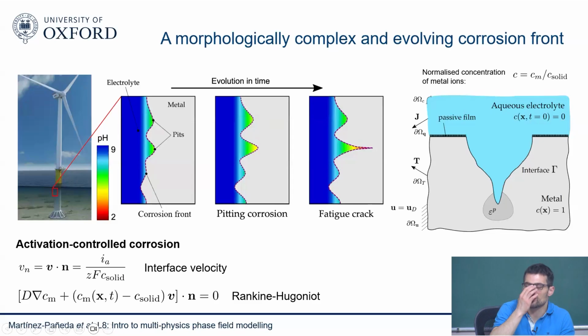And then, what happens in corrosion is that we have two scenarios. One is called activation control corrosion. The other one is called diffusion control corrosion. In activation control corrosion, we do know that the velocity of the pit, this is what you're seeing here, is governed by Faraday's second law. So you have corrosion current density, Faraday's constant, concentration of the solid, and so on. This is an equation that has a clear physical meaning, and it gives you how fast your pit grows. And here you have a Rankine-Hugoniot condition, which tells you what is the concentration of metal ions at the interface. This is what you're solving for, the CM, which you can normalize by C solid.